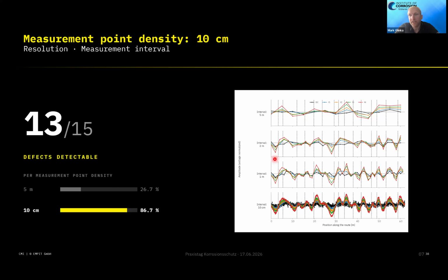So we are actually looking in this signal for the tiniest of the tiniest features in order to find the ones which are corroding, not for the big boys, because the big boys with a big amplitude are perfectly cathodically protected. And this is also what you see in the statistics. OGE, the biggest German operator, dug up over 200 features based upon amplitude and based upon the IR-free potential. And they found more or less nothing. They found one spot which they thought was actively corroding.